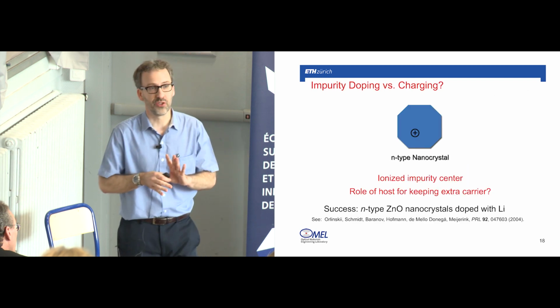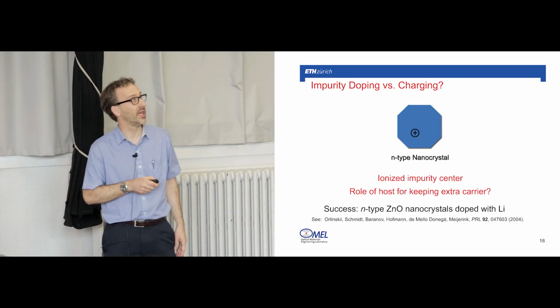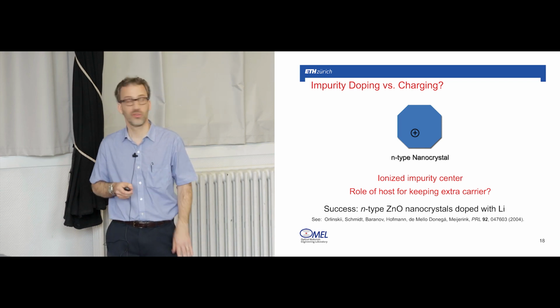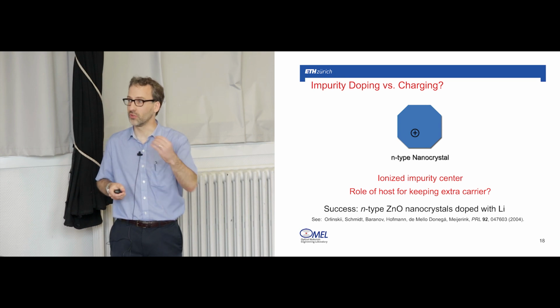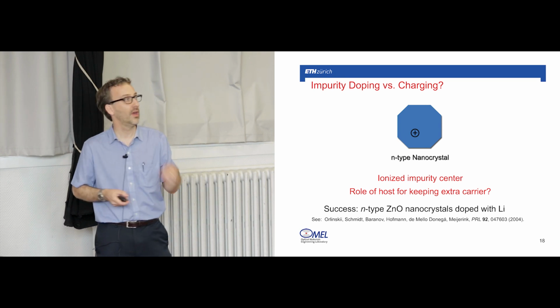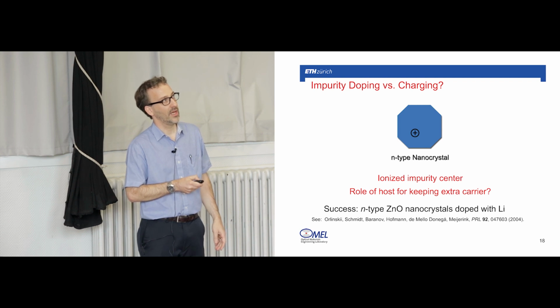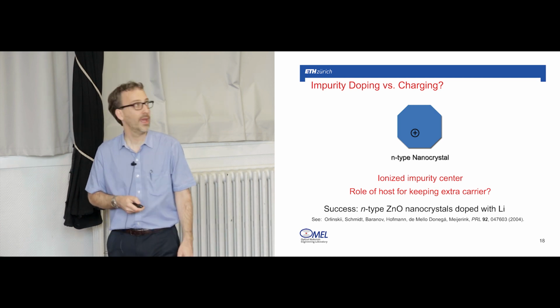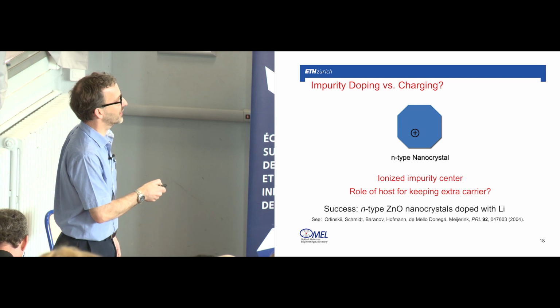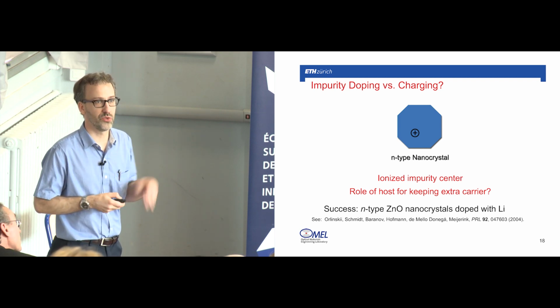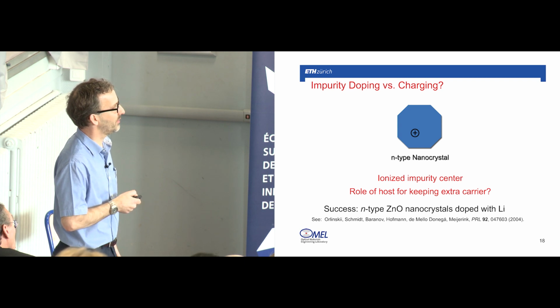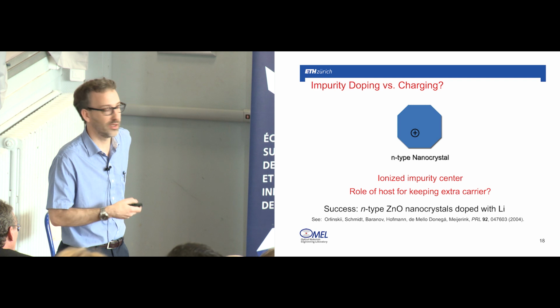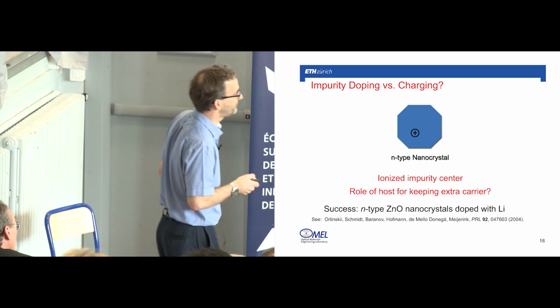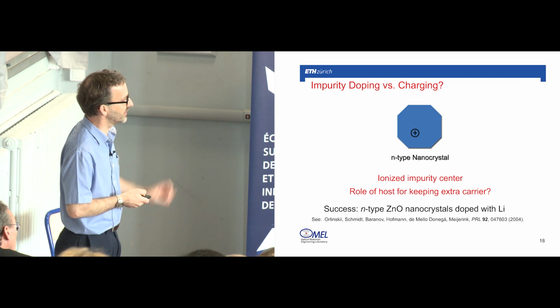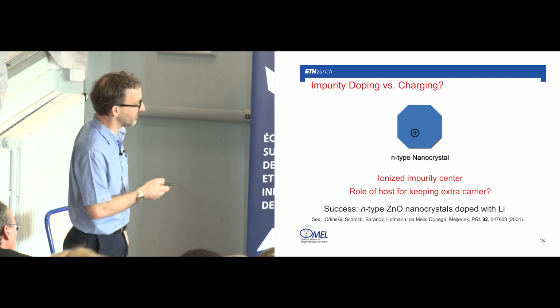Now, I do want to stop, though, and mention that although there's clearly a relationship between charging and impurity doping, there are also differences. If you charge a nanocrystal or reduce it, you're just putting an electron on the particle, or you can take it back off. If you have an impurity there and it ionizes, in this case, if it's a donor, you have your electron and you have your ionized impurity center left behind. And as we might expect, this electron can go off and do all kinds of bad things. It can reduce something in the environment and leave. And then we're going to be left behind with this ionized impurity, and that can also potentially affect the properties of the nanocrystals. So we have to think about the fact that we can have ionized impurity centers, and that's going to be important in the last part of my talk.